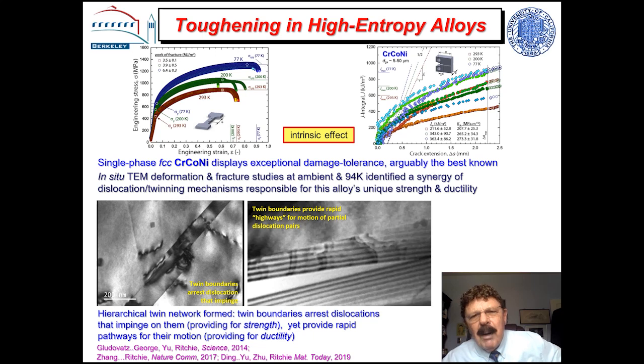This is toughening in high entropy alloys, metallic materials. This is purely intrinsic. These are fascinating materials. They have multiple principal elements. They often are single phase. This one's a cobalt, chrome, nickel, single phase alloy. These are the tensile tests at room temperature in brown.